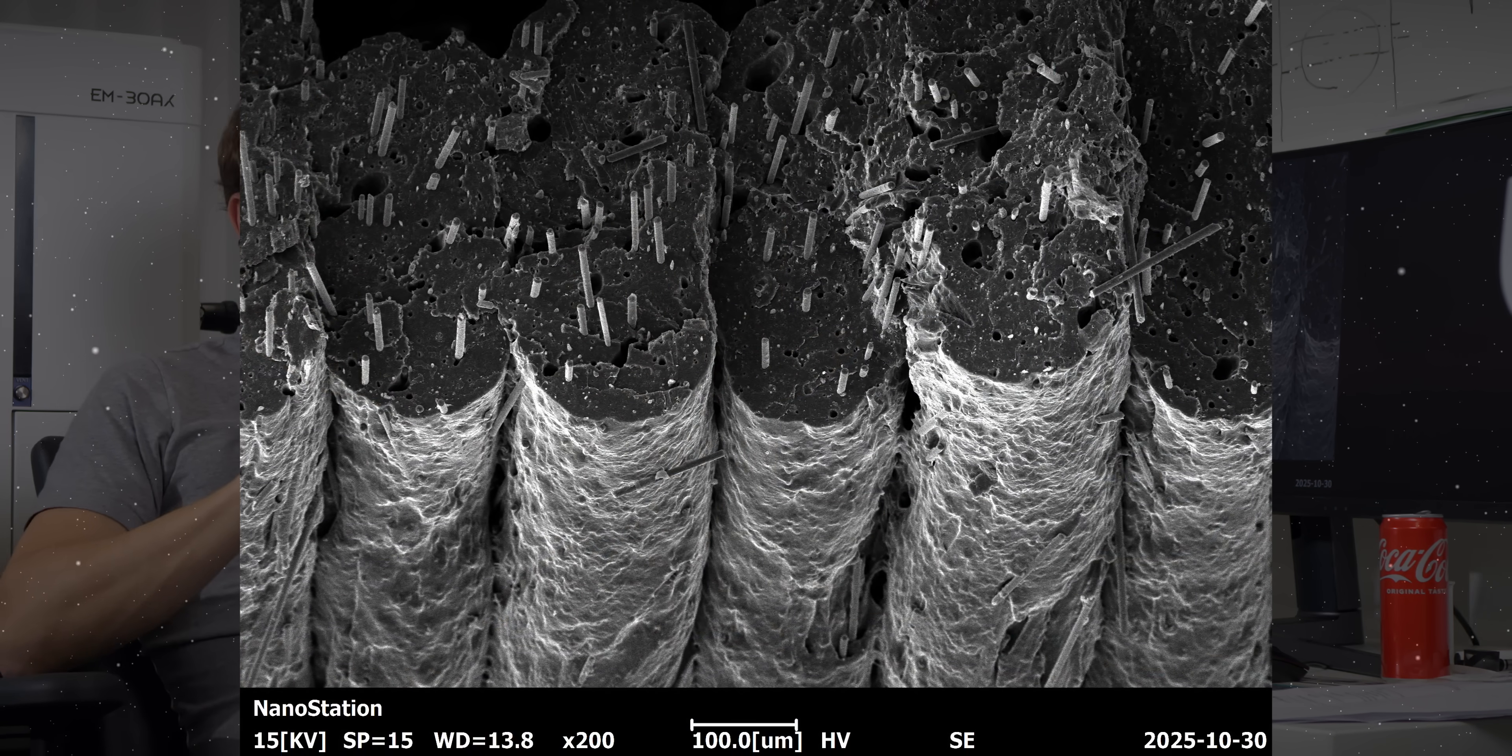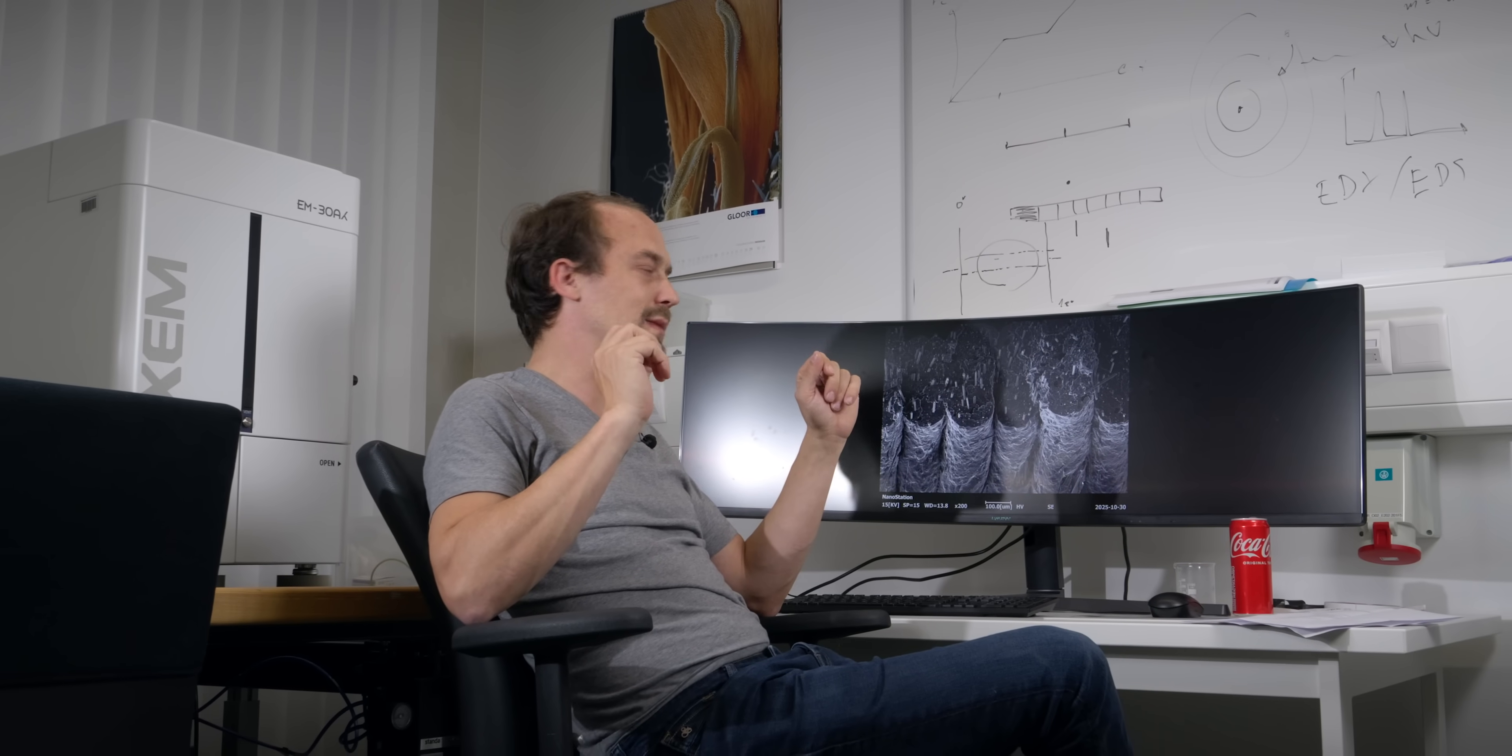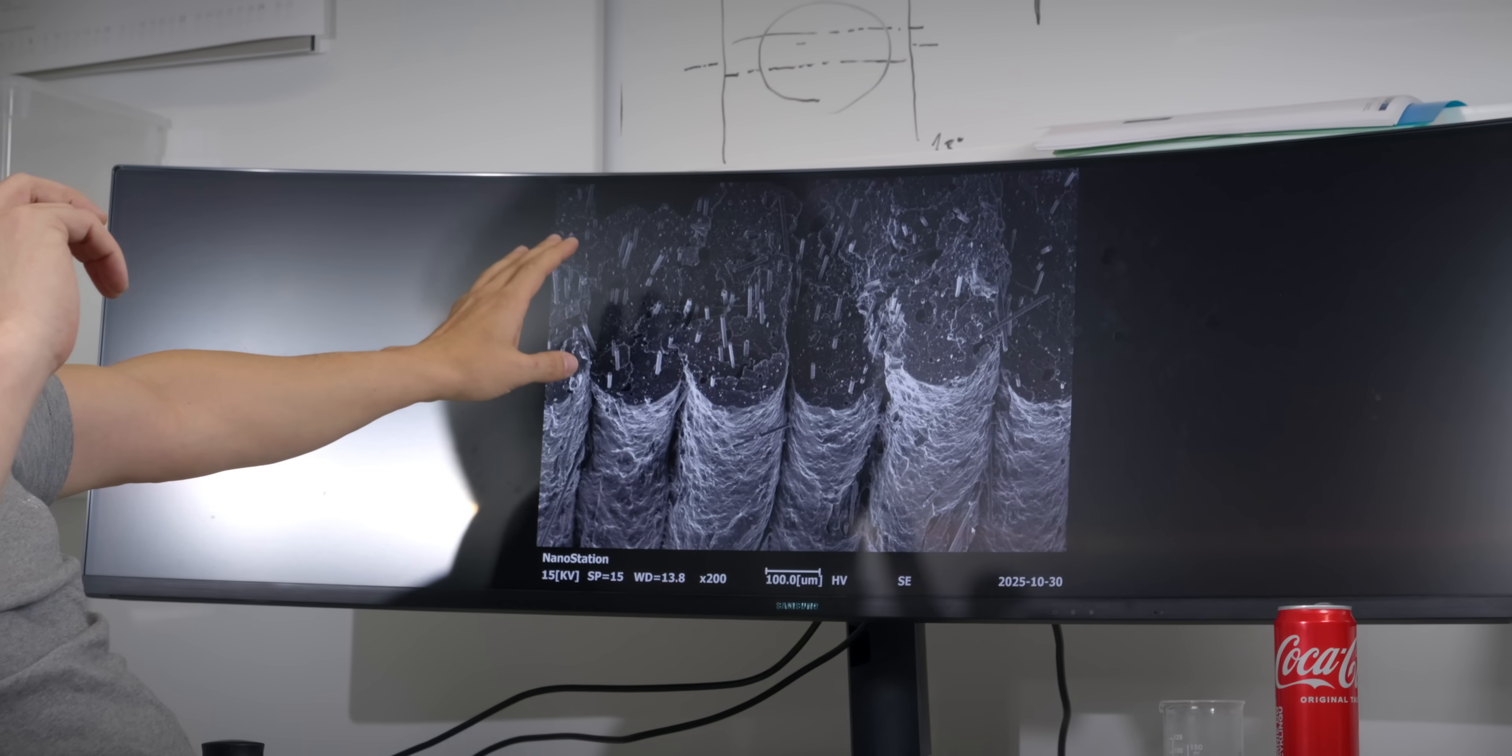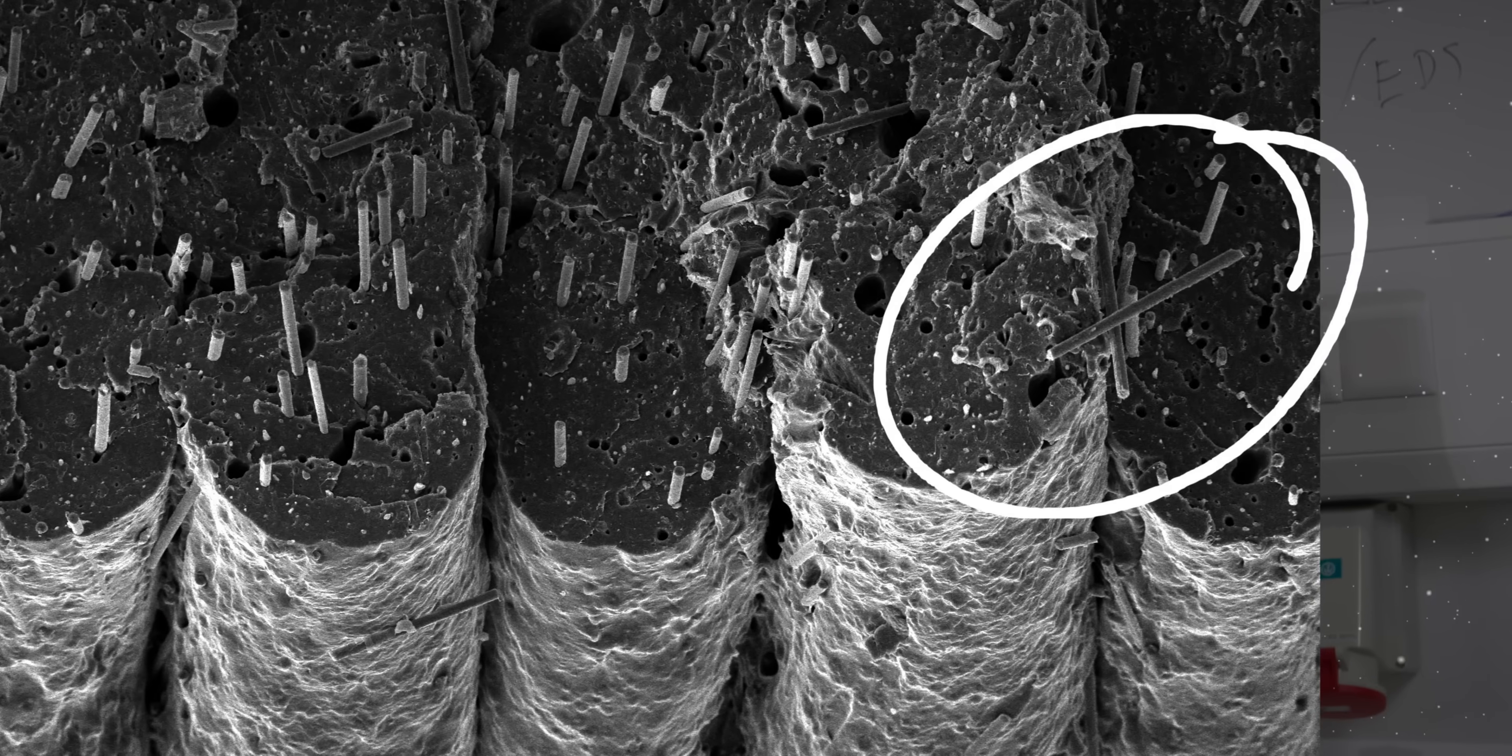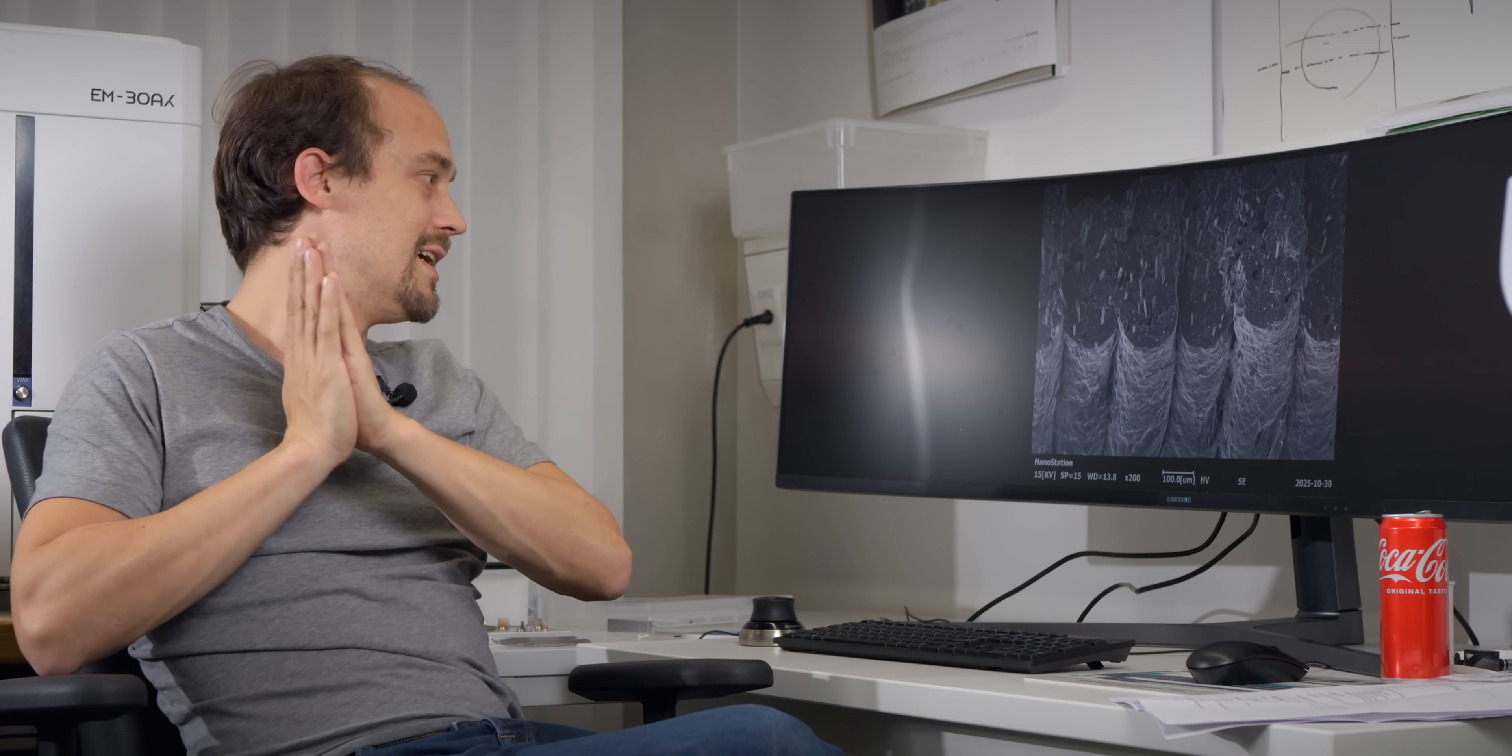Let's look at what we find out. This is an image of a 3D printed part with PLA carbon fiber reinforced. It's exactly 200 times magnification. As you can see, there is a whole mess of carbon fiber going on everywhere. But the one thing we can actually see is that all the carbon fibers that are not ripped out completely are actually aligned into the flow of the filament. That's something I already claimed, but that's something nobody argued about. That's just the way it is.